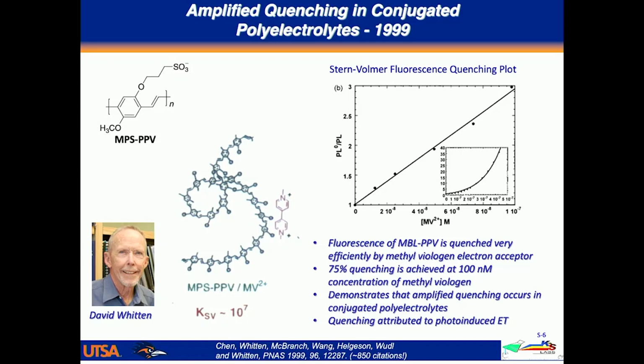And so these two got together and decided, well, what happens if we take Fred's polyanion and look at the quenching with methyl viologen? It turns out they saw the Swager effect. They saw what is called amplified quenching. I'm going to tell you more about the idea, but for those of you who know something about quenching already, they found that the Stern-Volmer constant was about 10 to the 7th per molar. What that means is that if you just add in the range of 10 or 20 nanomolar of this quencher ion, you can basically turn off the fluorescence of the whole polymer. So this pretty interesting effect brings together Swager's amplified quenching with the polyelectrolytes.